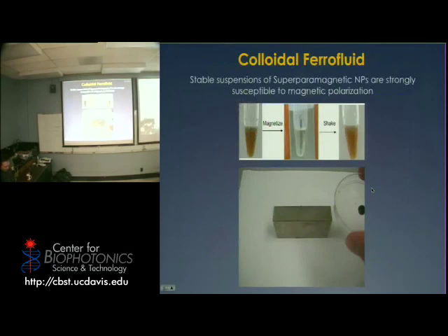I actually have some if you want to see, but in the biomedical sense, we call these ferrofluids. So you have a suspension of these particles, it's colloidal like the gold, but in this case it's magnetic. And they give you a clear solution and everything. If you put them close to a magnet, they go to the magnet, but when you remove the magnet and shake them up, they go back. In actuality, this is the behavior of the larger ones. The ones that are smaller don't really aggregate, but they have properties like this.